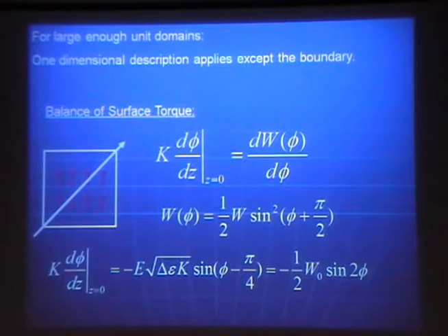And by assuming a simple planar condition, you can calculate the threshold electric field by means of the Gaussian flexoelectric contribution along with the anchoring energy. And you can just solve the equation as in the ordinary Fréedericksz transition.